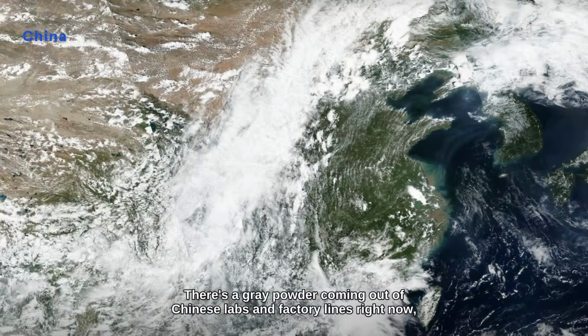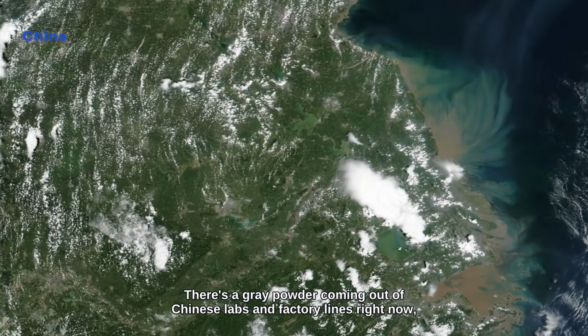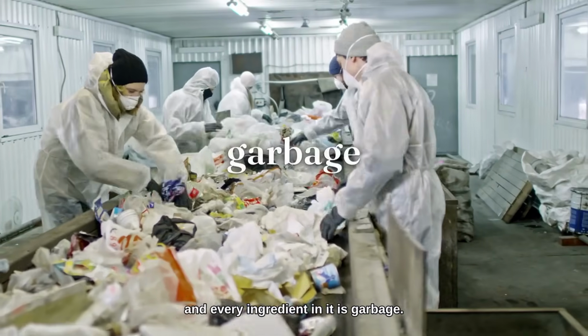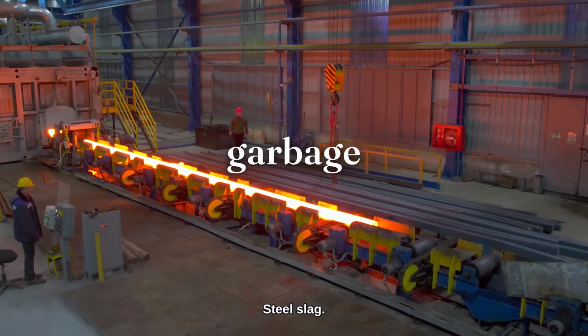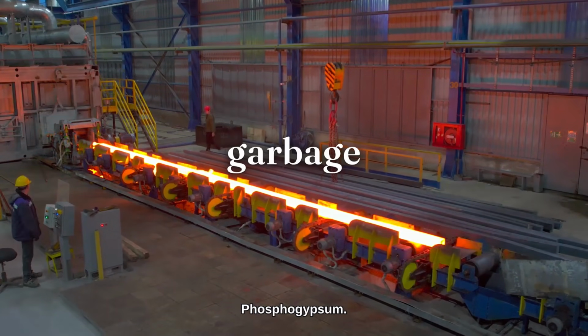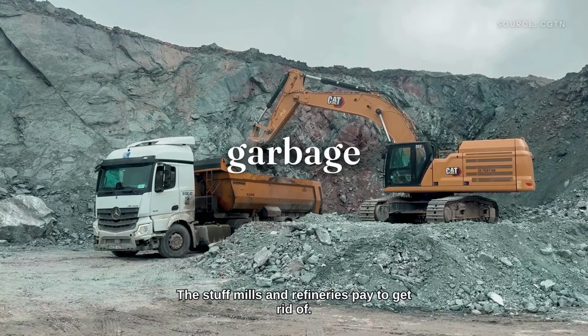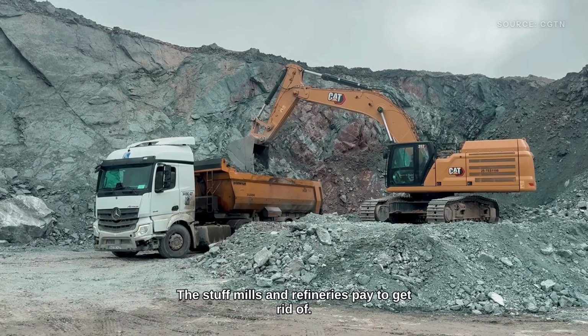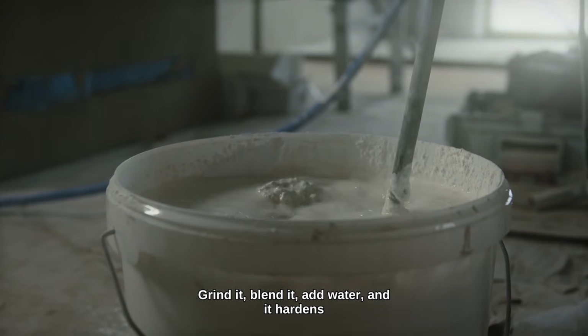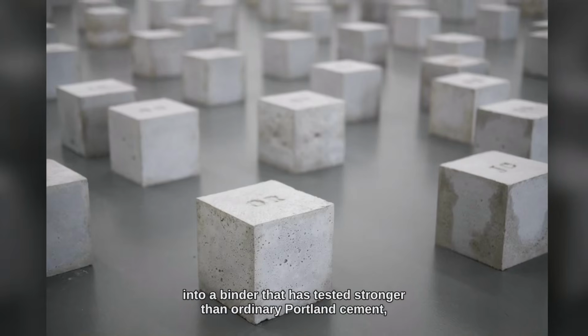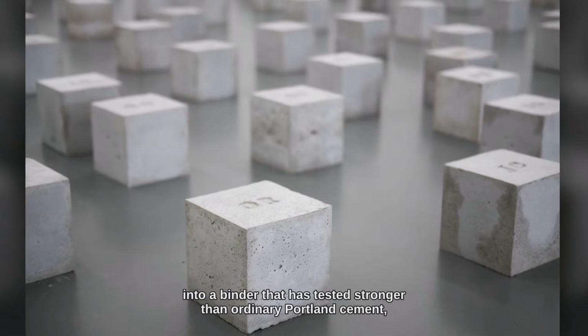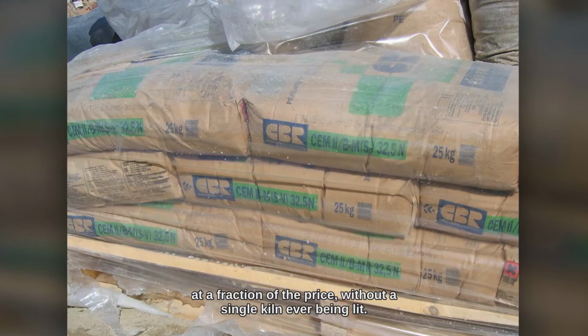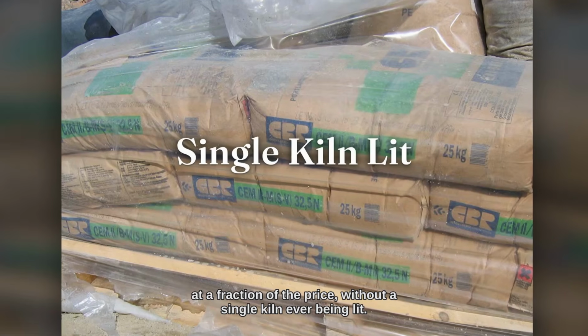There's a gray powder coming out of Chinese labs and factory lines right now, and every ingredient in it is garbage. Steel slag, red mud, phosphogypsum, carbide slag. The stuff mills and refineries pay to get rid of. Grind it, blend it, add water, and it hardens into a binder that is tested stronger than ordinary Portland cement at a fraction of the price, without a single kiln ever being lit.